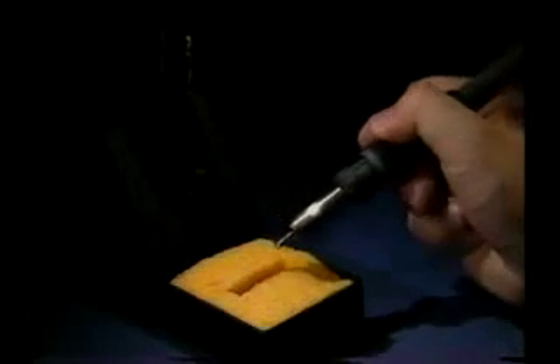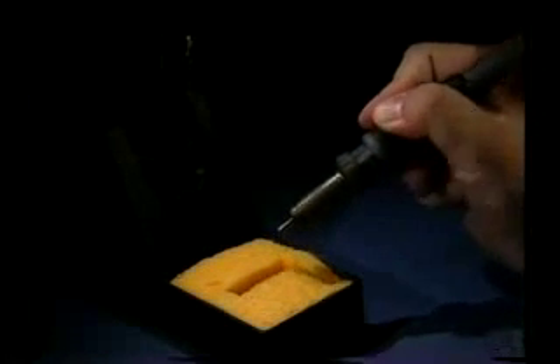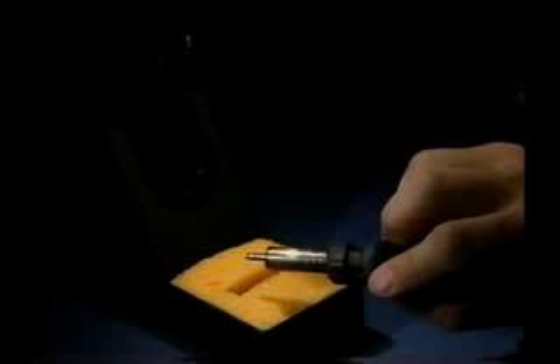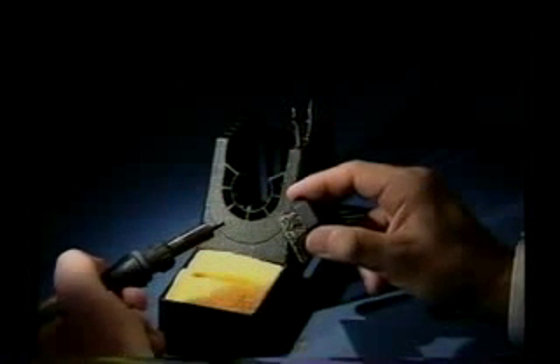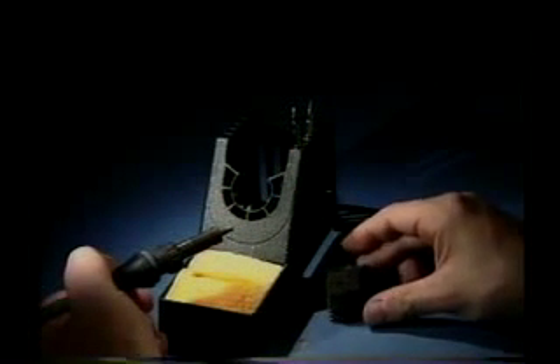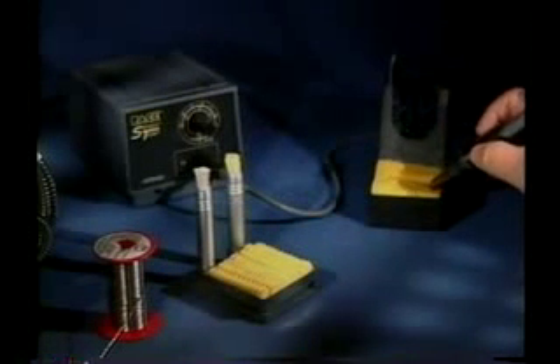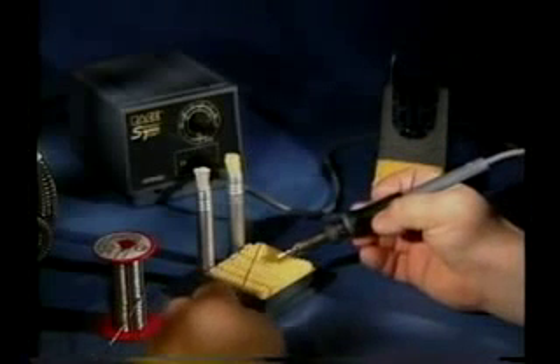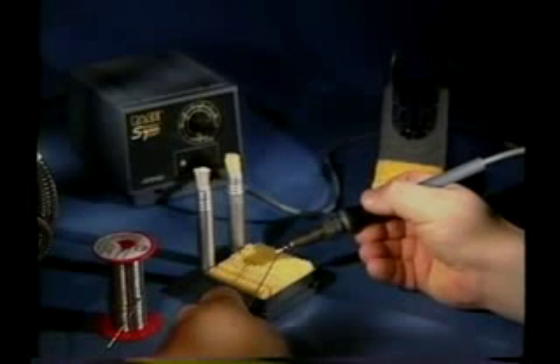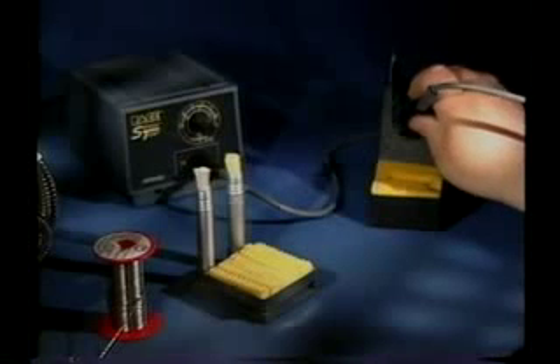Before we begin soldering terminals, it is important to clean the soldering iron. A clean, damp sponge should always be used to thoroughly clean the tip. Never use a wire brush to clean the tip because of the possible safety hazard of splashing hot solder into someone's face, hands, or clothing. A wire brush can also damage the tip of the iron. And when you're finished soldering, always give the tip a fresh coating of solder to cover the tip. Tinning allows the tip to last longer because it forms a protective barrier.